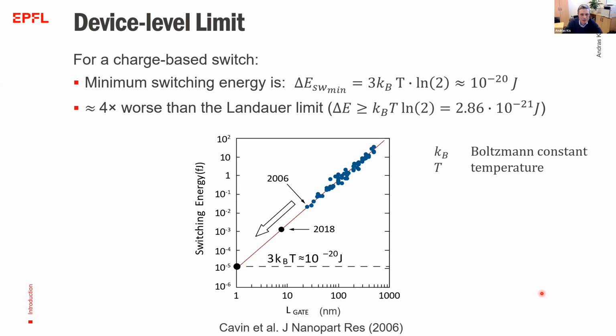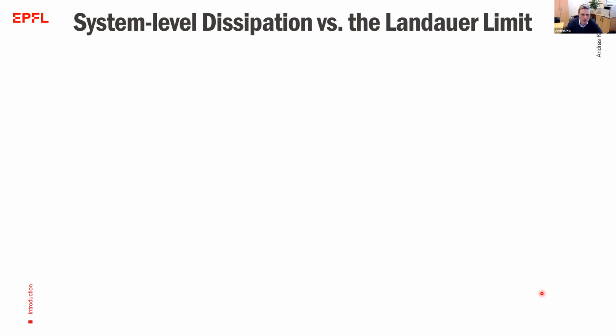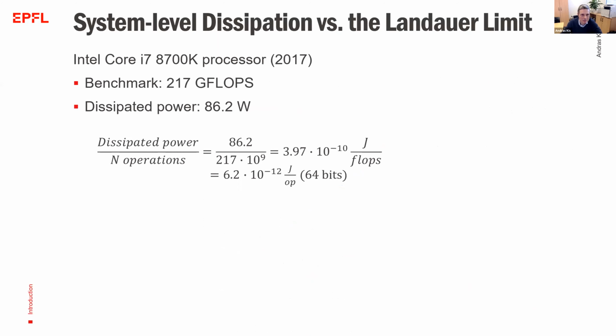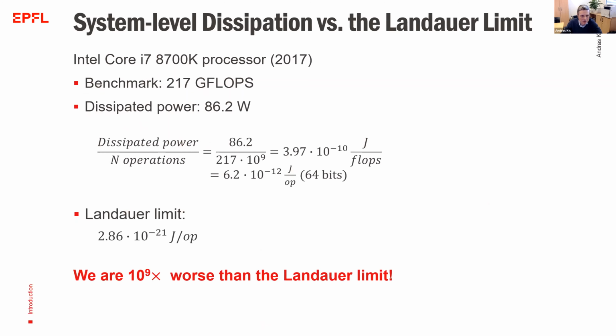But there is another part where a lot of energy is wasted, and that's actually much more pronounced than if you look at just a single transistor. And that becomes obvious if you start to look at a whole computing system, for example, a computer or a processor, and then you compare the power dissipation with the Landauer limit. So if you take a relatively high-end processor from a couple of years ago, and the numbers haven't really improved dramatically in the meantime, and if you look at some benchmark and how much this processor is dissipating while achieving some performance level, and you just try to calculate, in a very back-of-the-envelope type of calculation, what is the dissipated power per operation, you're getting that we are something like 10 to the 9, so basically 1 billion times worse than the Landauer limit on the level of an entire system. And this is extremely wasteful, of course.